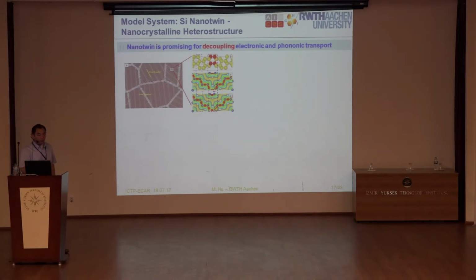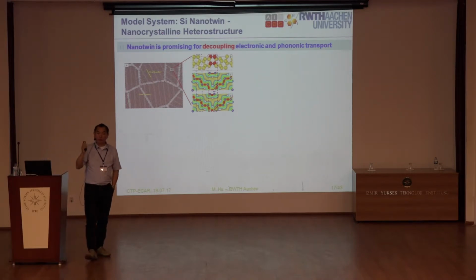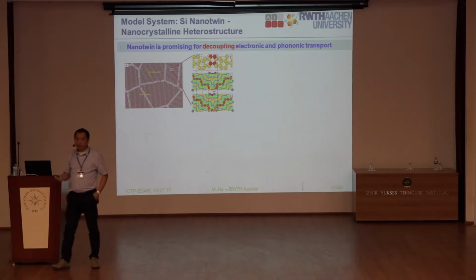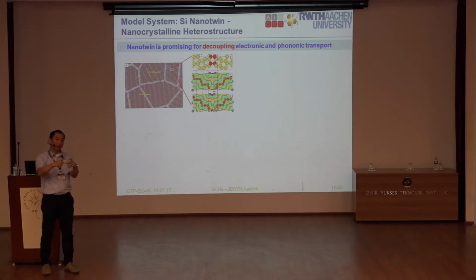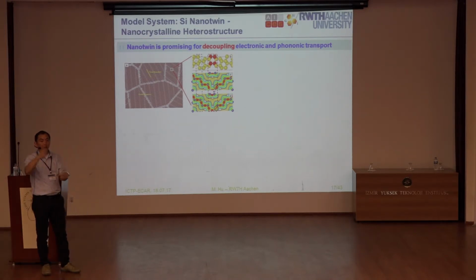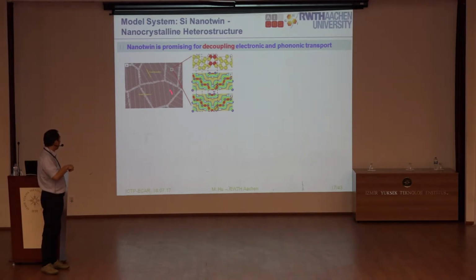We introduce a nano-twin inside the nanocrystalline. So you make silicon a nanocrystalline. Of course, everyone knows that if you want to make silicon a very good thermoelectric, first you have to nanostructure silicon, because the thermal conductivity of silicon is so high, right? It's not good. And then you make it nano size, and nano size itself is not enough. You have to put lots of nano-twin inside.